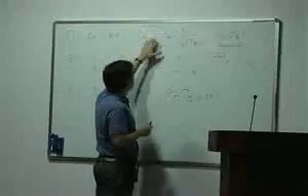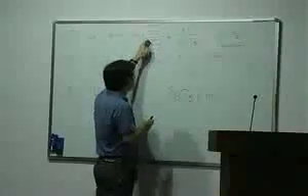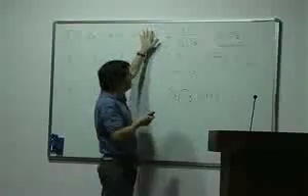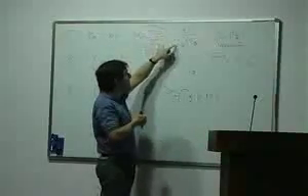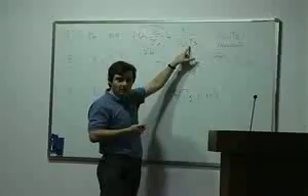So this means that if it's true that tau alpha has this expression, since tau alpha at Tg is just always 100 seconds and tau 0 is picoseconds, this is equal for all liquids in a trivial way. This is equal for all liquids at Tg, but it is also equal to this quantity, so this means that Sc at Tg, the configurational entropy at Tg, should be the same for all liquids at Tg.